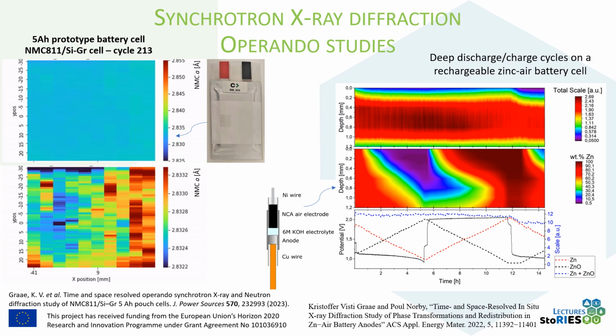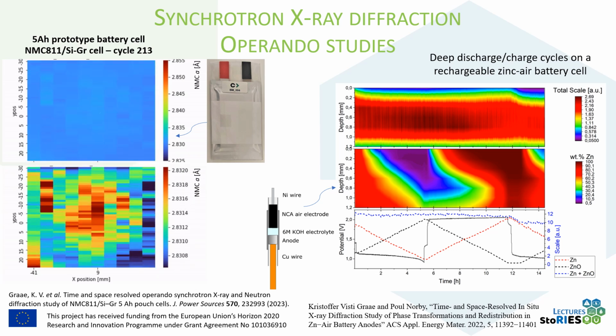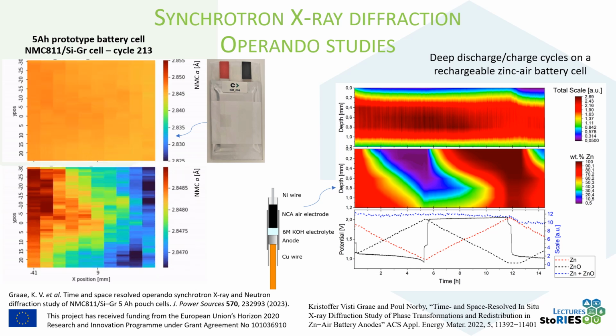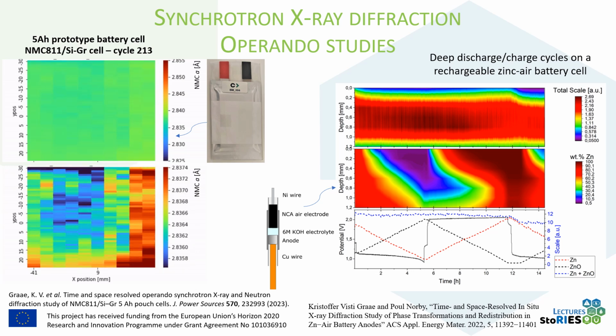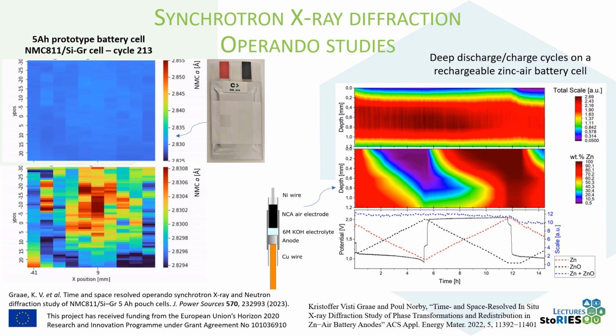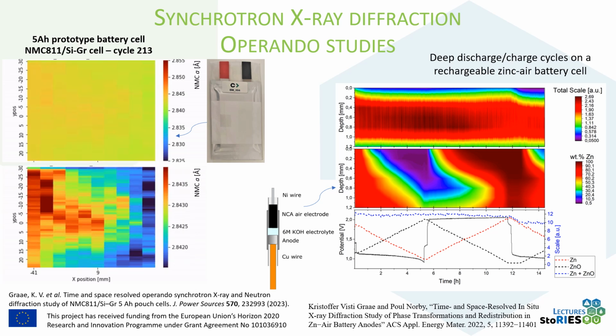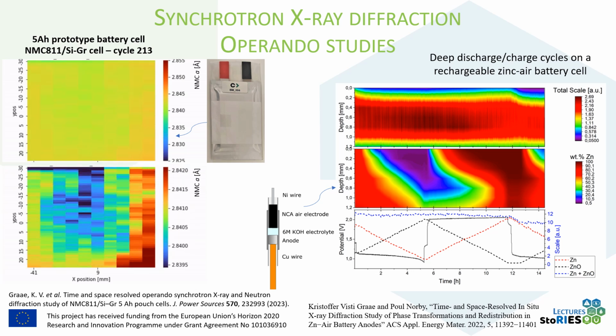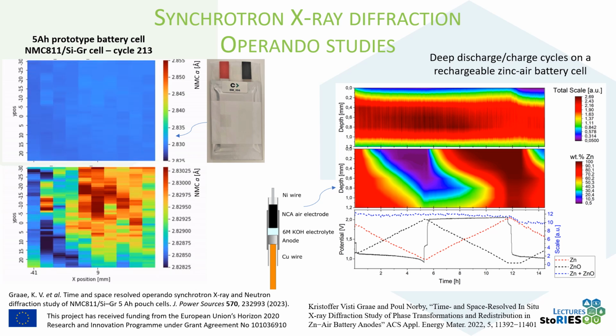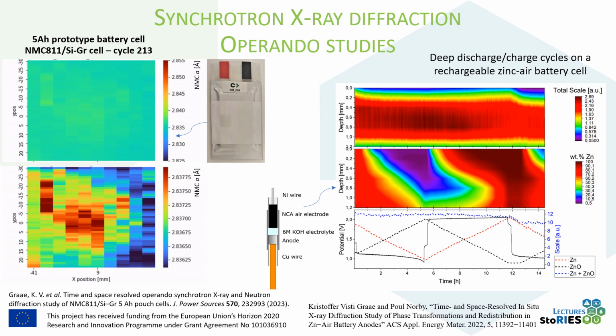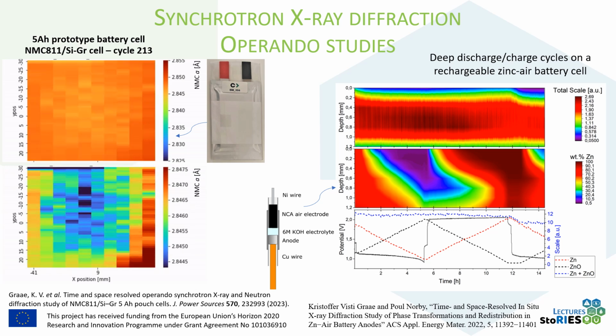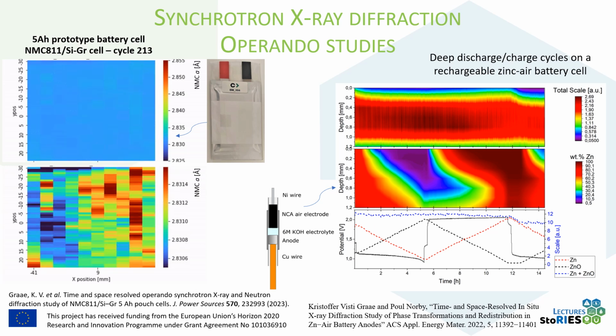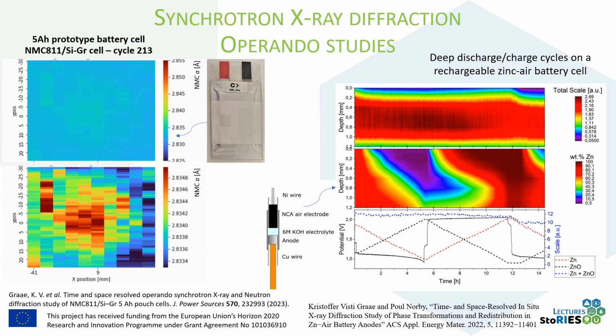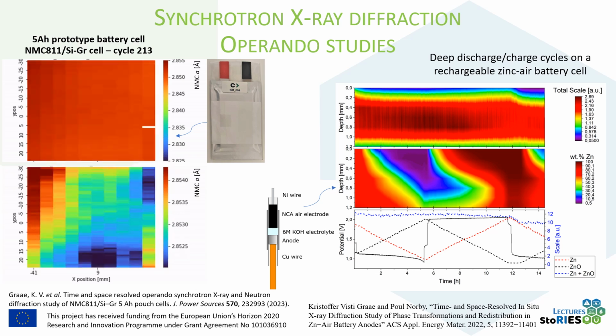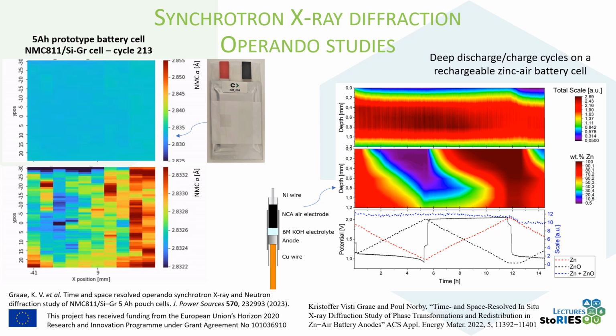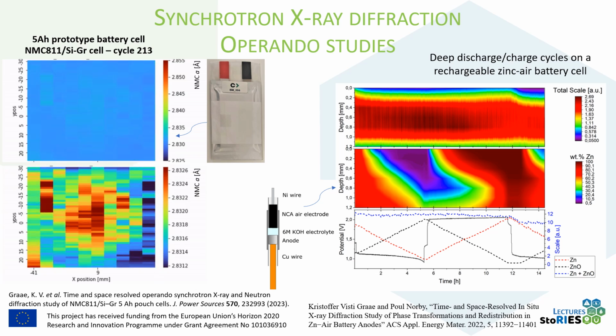The right-hand side shows a study where we followed the phase distribution between zinc and zinc oxide in a rechargeable zinc air battery. The battery cell was built in a capillary, giving access to perform spatially and time-resolved synchrotron X-ray diffraction studies. The map shows the phase distribution as a function of time and height in the anode, given as weight percentage of the zinc metal. As the discharge progresses, a reaction gradient is clearly developing through the anode. On the following charge cycle, reduction of zinc oxide to zinc is observed, leading to a more complex phase distribution gradient.